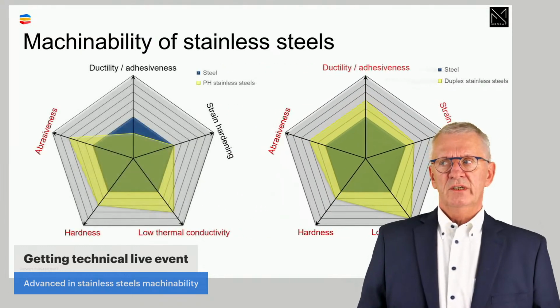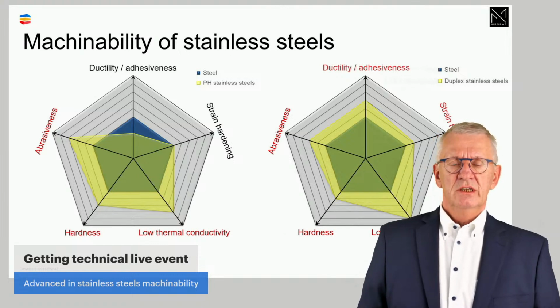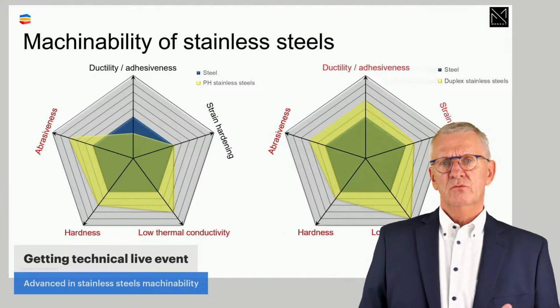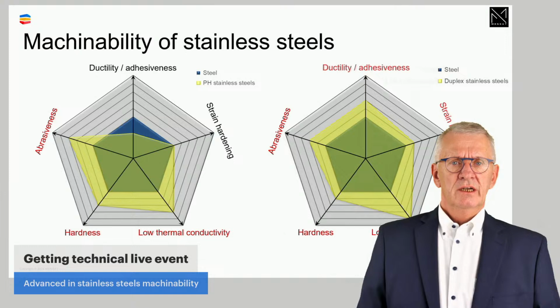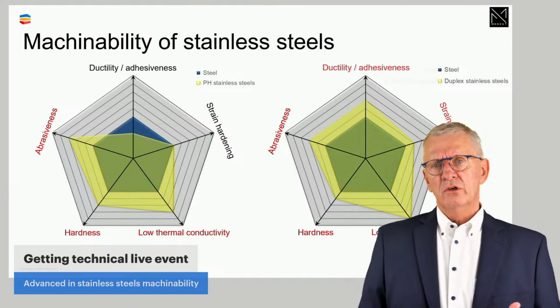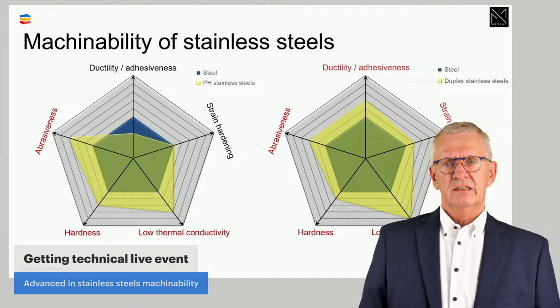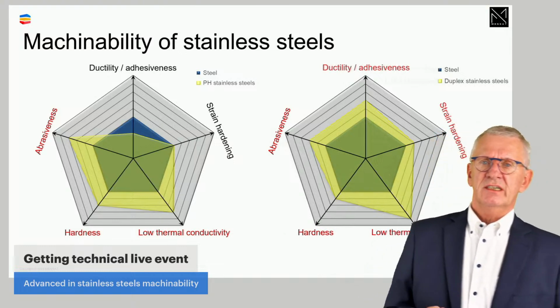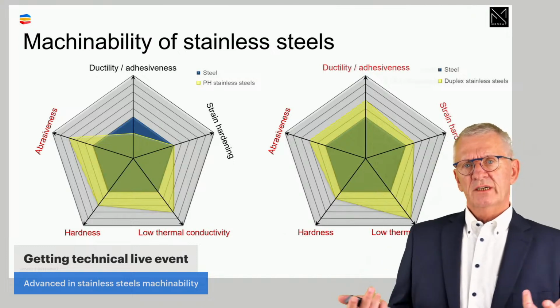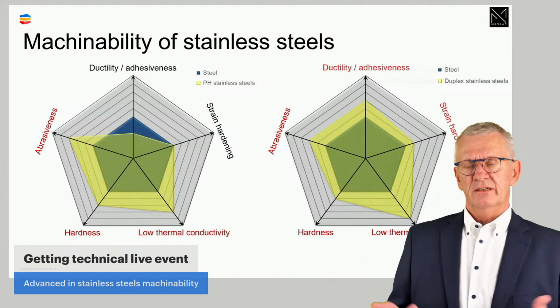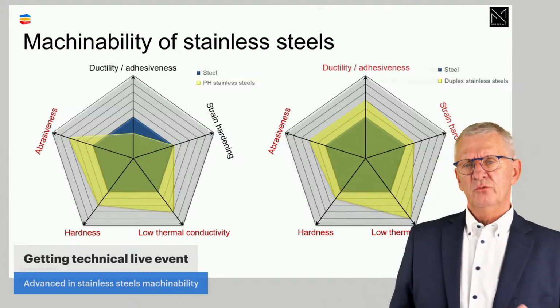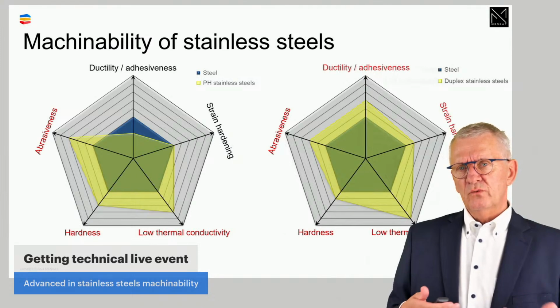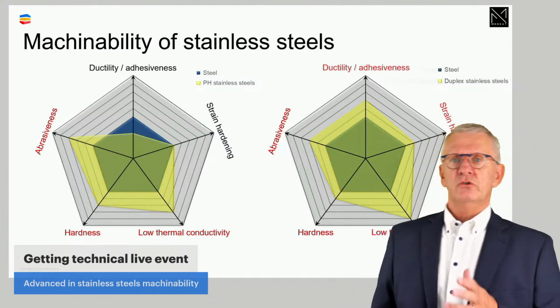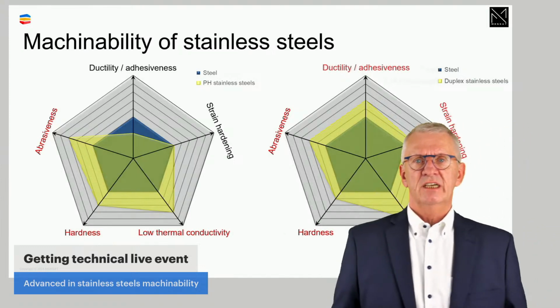To make the picture complete, with PH stainless steels, precipitation hardening stainless steels, you have to worry mainly about abrasiveness. Ductility will be less of a thing. Chip control will be easier than normal, but abrasiveness is the thing to worry about in PH stainless steels. Duplex stainless steels, as I said, if you compare them with steel, everything is more severe there. But the thing with duplex stainless steels is that we don't know exactly, workpiece by workpiece, which one will be the prevailing one during the actual operation. For sure, low thermal conductivity is also a major thing there.